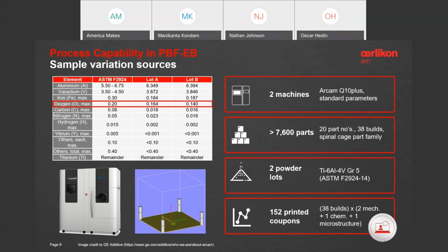A few words about our sampling strategy. A grand total of 38 EBM builds were produced, 18 of which were printed on machine number 1, and the remaining on machine number 2. Our mechanical inspection plan for lot release requires 4 test coupons to be printed with each production build. So the total number of printed coupons was 152.